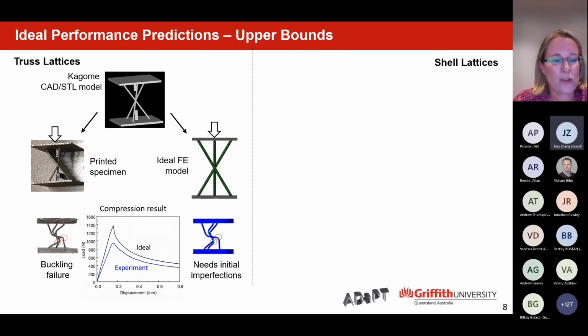And that's what we see in natural structures as well. They have imperfections. So here we're introducing some minor initial imperfections, very small, and we can capture the buckling failure well, but we still overpredict the experimental results, and we made sure that the finite element model has the same volume based on weight and so on.